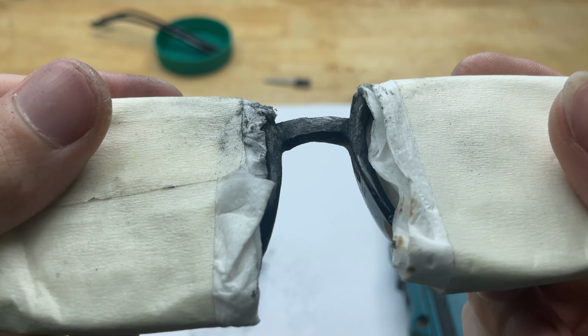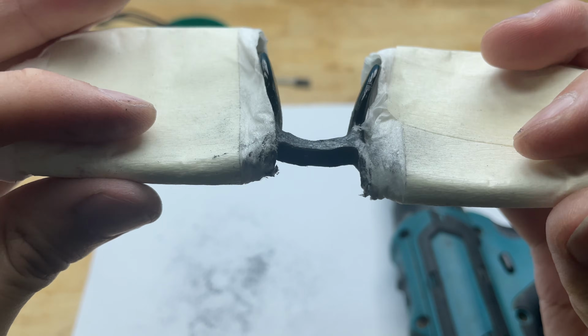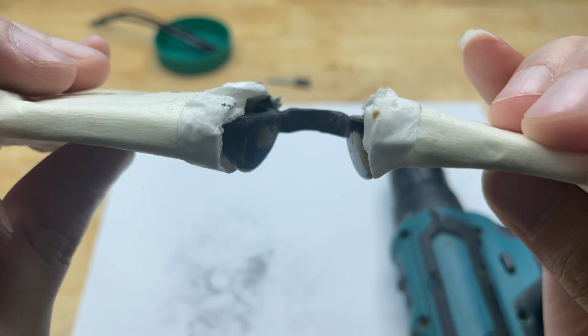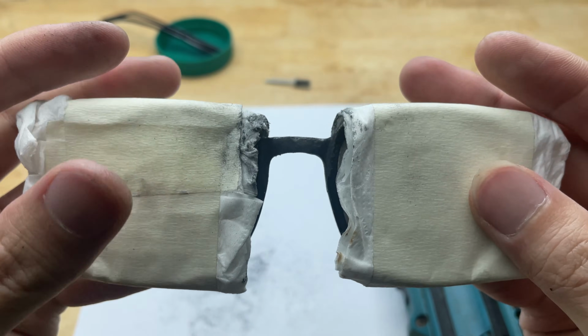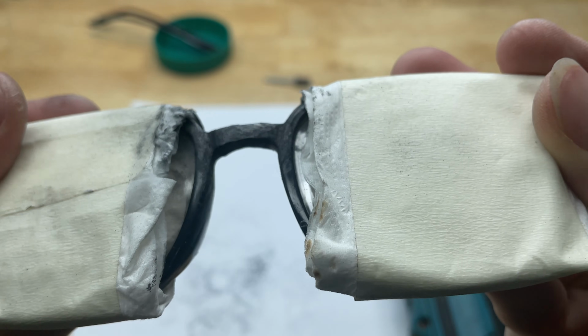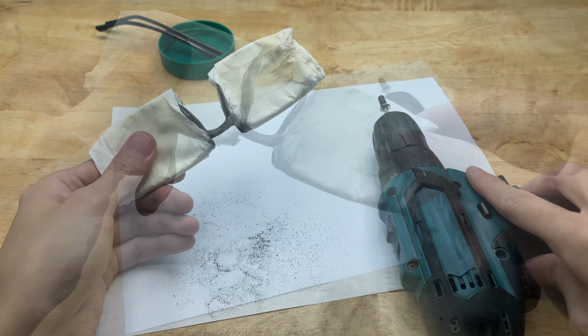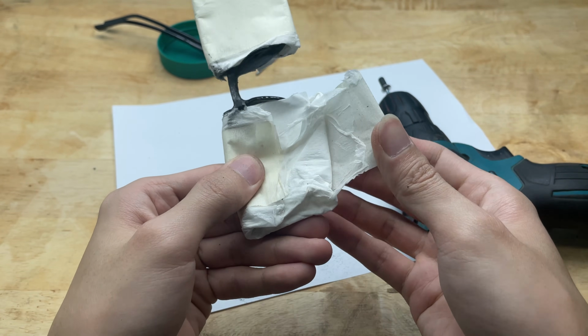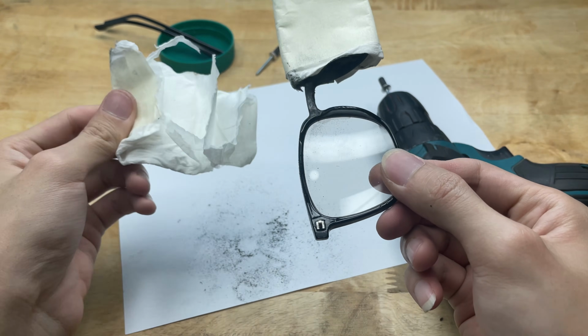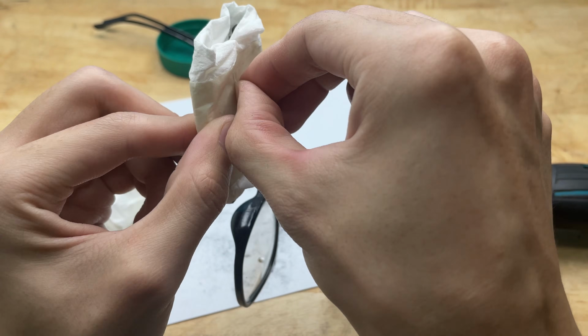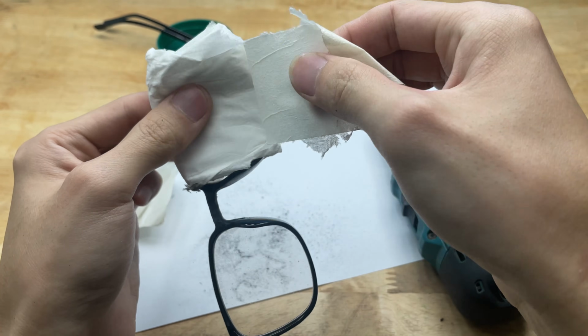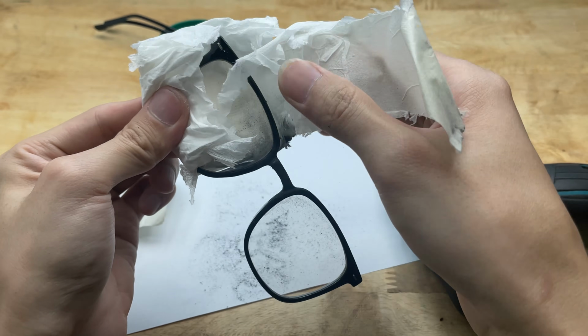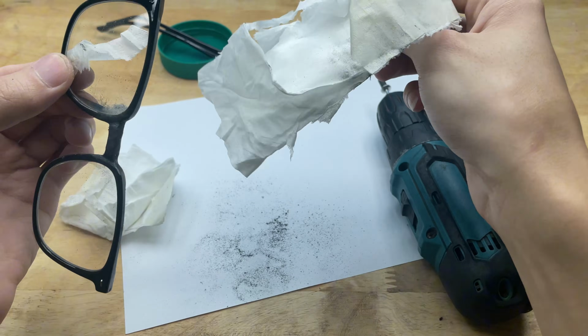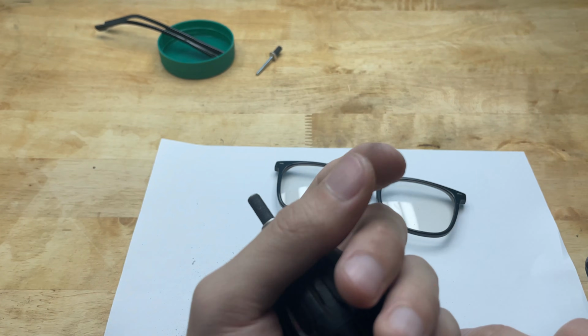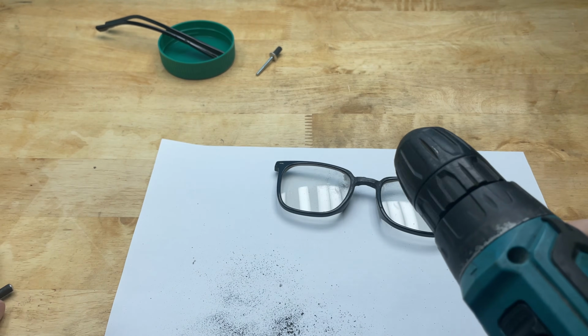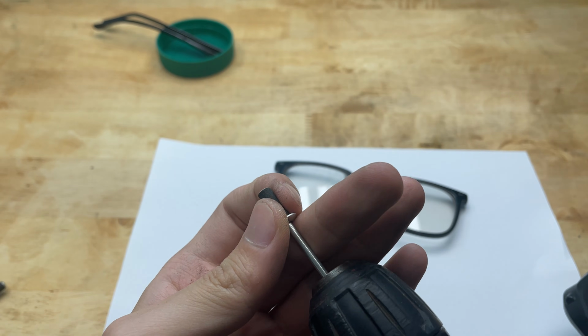After completing the coarse sanding step, the bridge area has been significantly leveled, with most of the large bumps and excess plastic removed. The repaired section now appears more aligned with the original frame. Although the surface is still slightly rough and shows small scratches left by the coarse sandpaper, the overall shape has been clearly restored and is ready for the fine sanding stage.